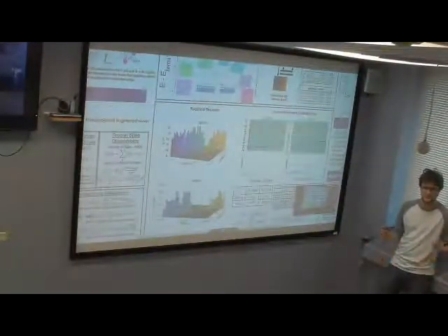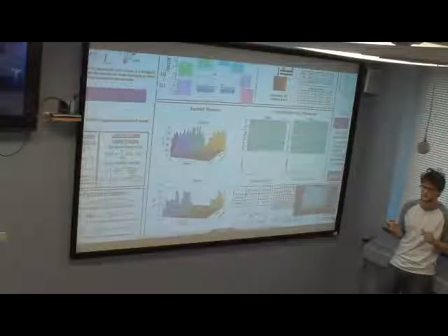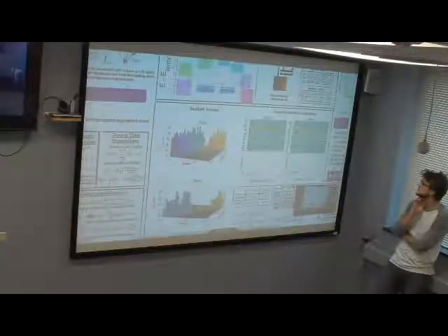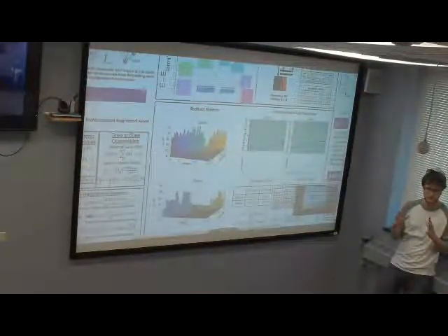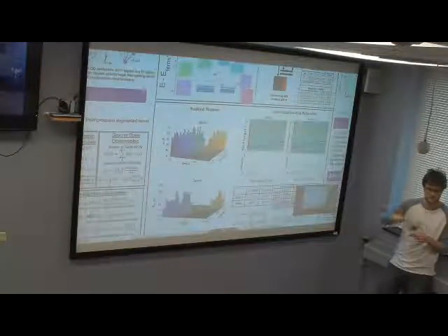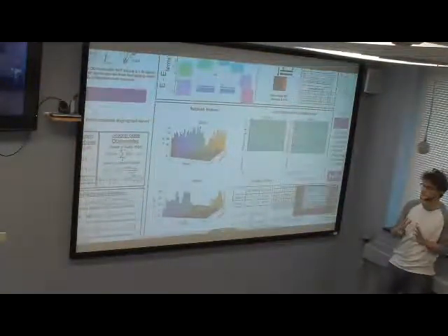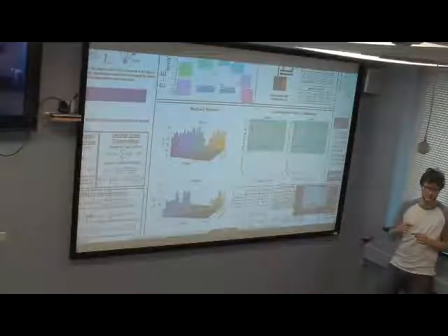I didn't exactly figure out the physical reasoning behind this, because with spinors you can't really compute orbitals for them, so you can't compare orbitals from the spin alpha with orbitals from the spinor. But I would suspect that spin orbit coupling tends to shrink your orbitals due to faster motion, like it contracts your orbitals. So if your orbitals are more contracted, there's going to be less spatial overlap for it to be non-orthogonal with it. That's the best idea I have at the moment.